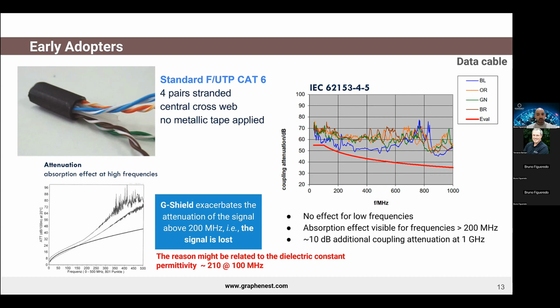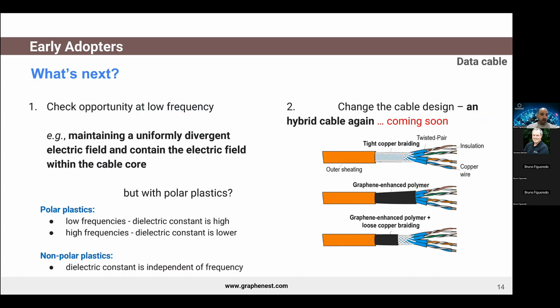Right now, we are actively researching and developing solutions to address these challenges, but we don't know yet where we're going to end up. Looking ahead, there are two different things that we can explore for data cables. So first of all, is to check the opportunity at low frequency, but for this we need to maintain and contain the electrical field within the cable core. But for this kind of application, maybe polar plastics might not be the right solution. We need to check, because at low frequencies, the dielectric constant is typically high, while at high frequencies, the dielectric constant is typically low. Maybe the best solution will be to use a non-polar plastic, because its dielectric constant is independent of frequency. But we need to check.